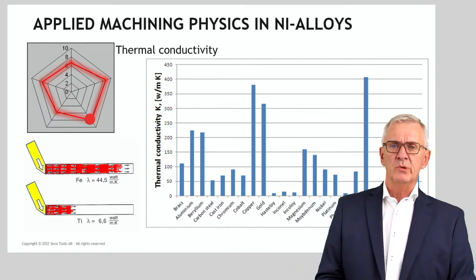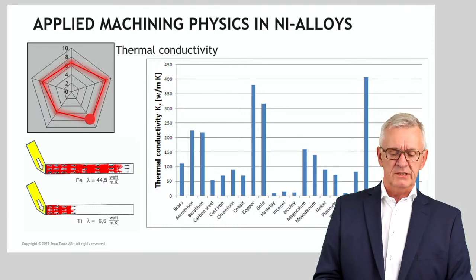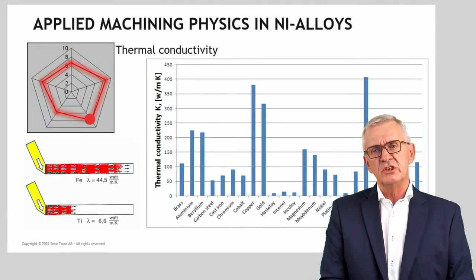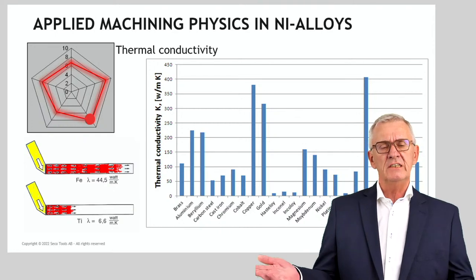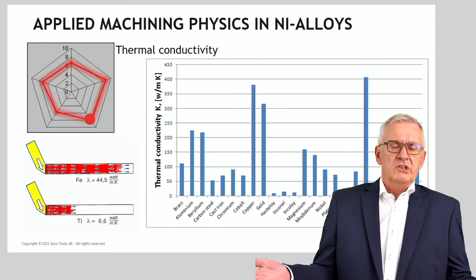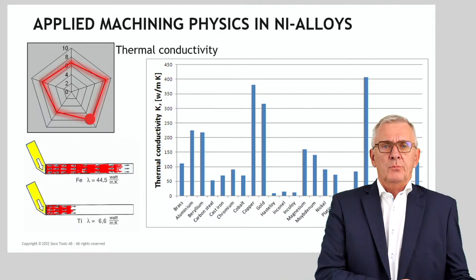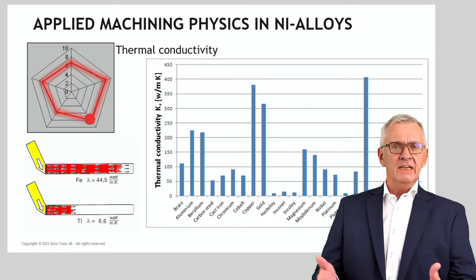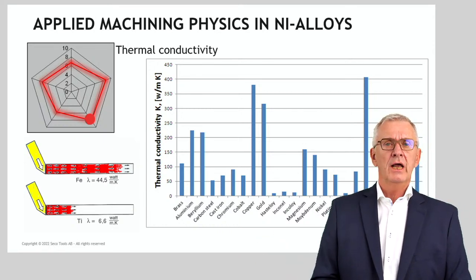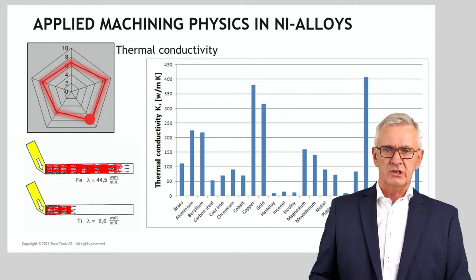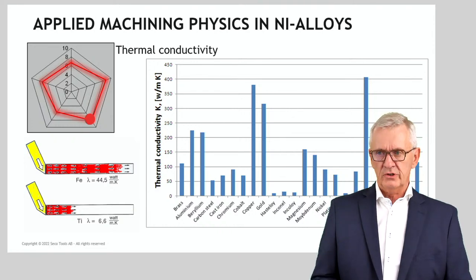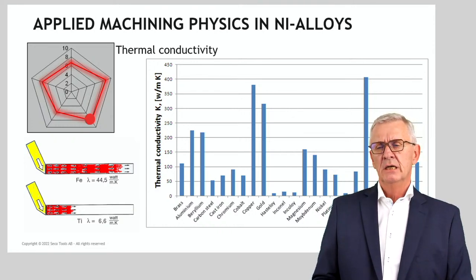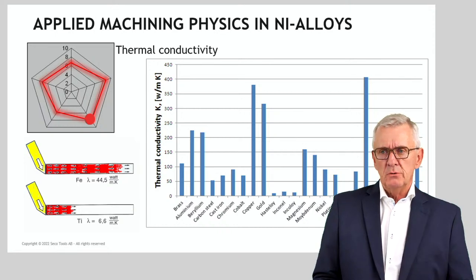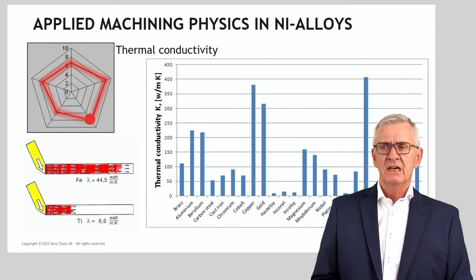Nickel-based alloys, titanium-based alloys, have much lower thermal conductivities. The heat does not go into the chips. But the heat needs to go somewhere. What does the heat do? It doesn't go to the workpiece, low thermal conductivity. Then it goes to the tool. And that is something that's going to affect the tool life very considerably. So thermal conductivity, next to strain hardening, my personal belief is that thermal conductivity is the other thing you have to really